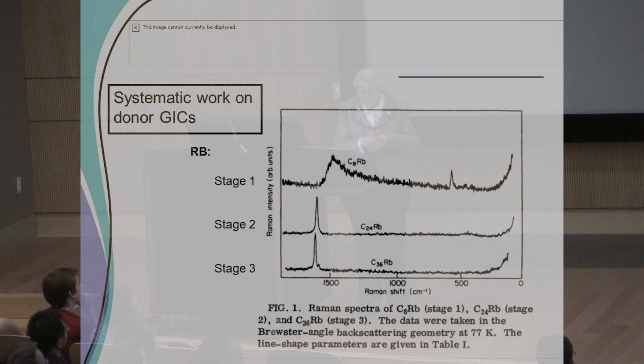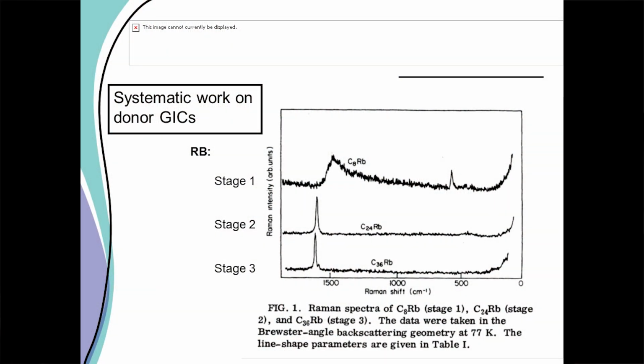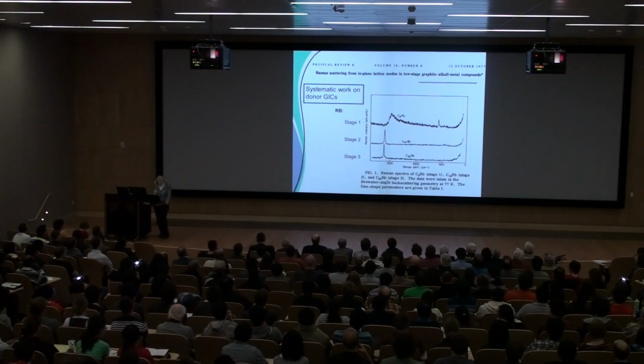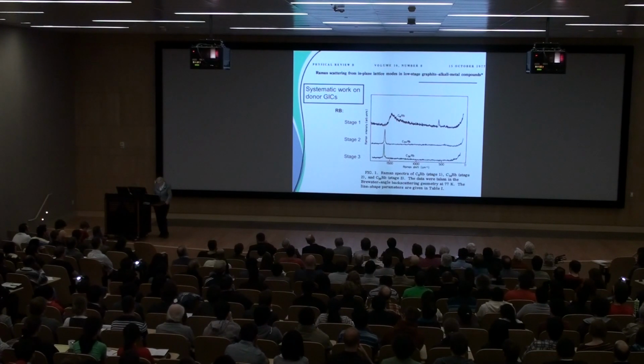So we put in materials that gave electrons to the graphene, and we had materials that took electrons away. We had both kinds. With the alkali metal intercalation, this is rubidium, which went between the layers. Rubidium has one free electron per atom, so those electrons could wander into the carbon system. So that's the idea with that.